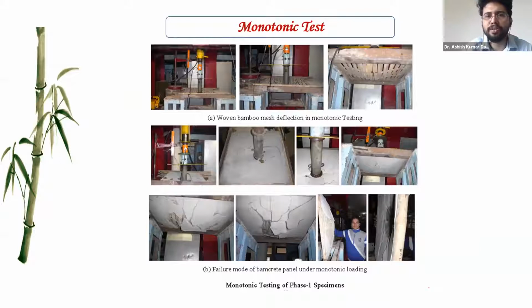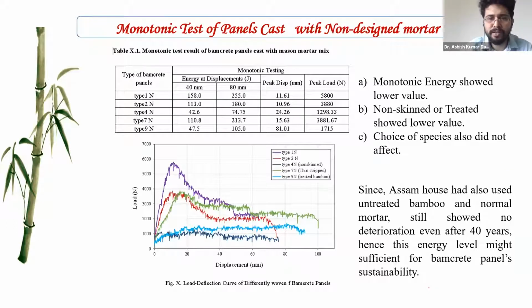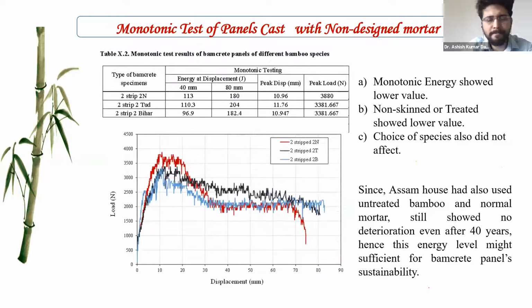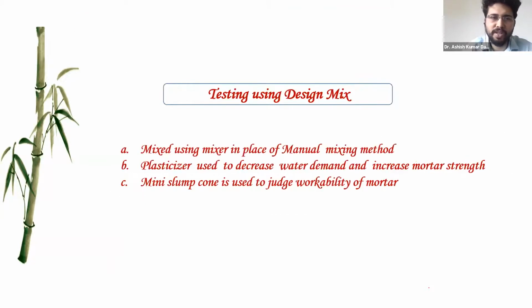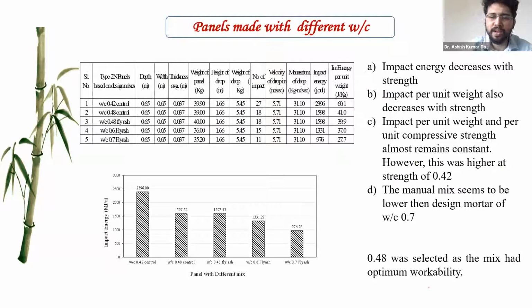This is the monotonic testing of the panels. This is the load versus deflection curve, and the non-skin strips fabricated panel showed very little strength. The variation of the species, different species also we tried. There is not significant variation we marked in the panel system, especially the strength carrying capacity when we consider the static loading test. Using different design mixes from 0.4 to 0.7, the panels were cast, and the impact energy study was conducted.